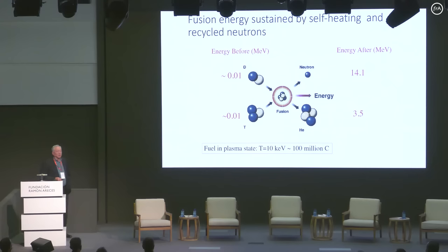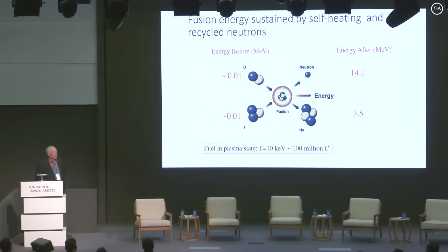I'll just walk you through this, because fusion sounds so exotic, but it's actually rather simple. This is the energy scheme of fusion. You take the fuel, which is called deuterium and tritium, the heavy forms of hydrogen, and you push them together. They fuse together, and it releases a helium particle and a neutron. The energies of the particles, again in this unit of MeV, start at 0.01, and afterwards you can see they're more like around 14, for a total of 17. This is enormous energy gain. This is why fusion is so attractive.